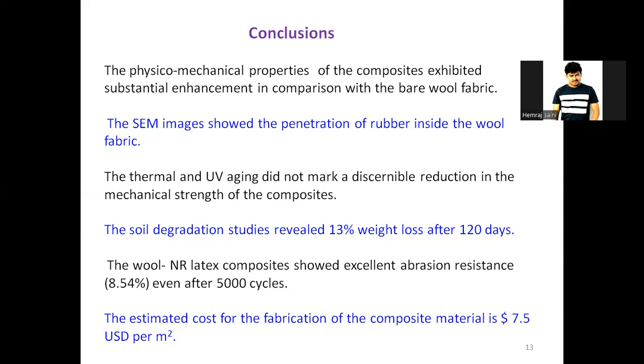Now, the 13% weight loss after 120 days, we assume is because of the degradation of the wool fiber, not of the rubber, because the rubber became very hard, and after vulcanization it's very difficult to degrade. Now, the abrasion resistance we also checked, and we found that it's excellent. After 5,000 cycles, we found only 8.54 percent reduction in weight. And we also calculated the price for the fabrication of the composite, and it's found to be around 7.5 USD per square meter.